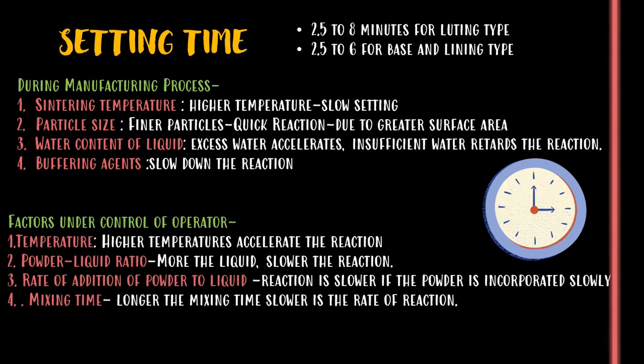The factors under the control of the operator are: temperature — higher temperatures accelerate the reaction; powder to liquid ratio — more liquid means slower reaction rate; rate of addition of powder to liquid — reaction is slower if the powder is incorporated slowly; and mixing time — longer mixing time means slower rate of reaction.